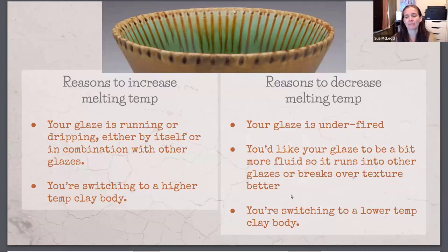Sometimes you want your glaze to be more fluid so that it can run into other glazes like this. Like I would design these bowls with these little divots on top because I was using very runny glazes, and I really liked how the brown glaze ran into the turquoise. And so that's a reason why you might like your glazes to run, as long as they stop before they hit the kiln shelf.